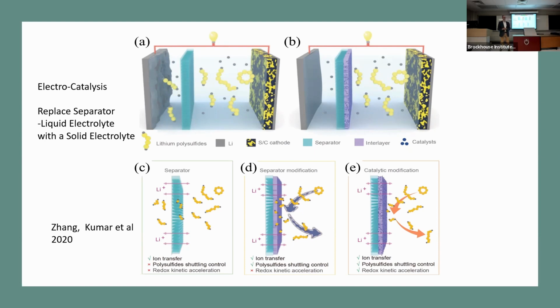But if you use the solid electrolyte as a substrate, you can't make it very thin. Then it's very resistive. It's not conductive enough. Yeah. So you can imagine there are many, many such problems. Okay. If you have a solid electrolyte which is made out of a ceramic, you have to sinter it.